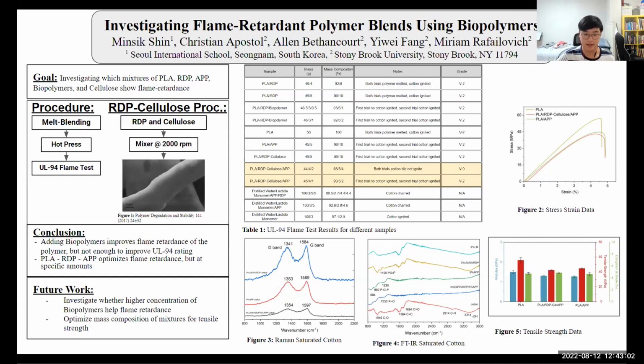However, we did note that slightly changing the APP amount did make it not flame retardant, as you can see below the highlighted one with the 90% PLA that yielded a V2 grade. The reason why we tried to minimize APP was, as you can see in figures 2 and 5, if we include APP, that significantly reduces the tensile strength of the polymer. So that's why we're trying to optimize the amount of APP so we can make a mechanically sturdier polymer.